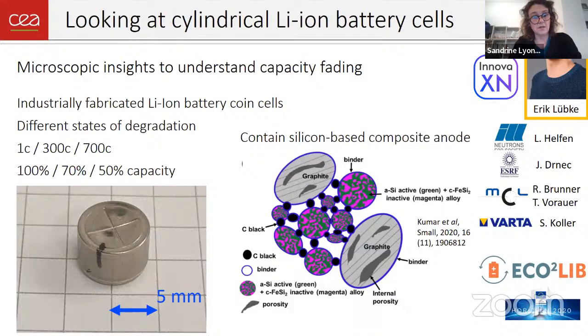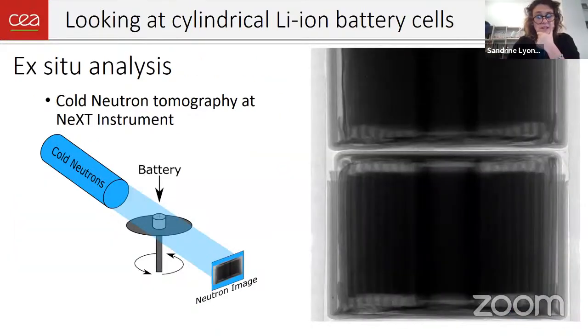And this cell contains a very complex silicon-based composite anode again, and a standard, let's say, high voltage cathode of the NMC family. So what Eric started doing is taking some neutron tomography, so it's not imaging anymore, it's tomography, and it's ex situ on the cells received from the industrial partner, using NeXT, which is a neutron tomography instrument at ILL. You see here the two cells located in the sample holder, and you can take a radio of this one, and if you rotate the sample, then you make the full tomography.